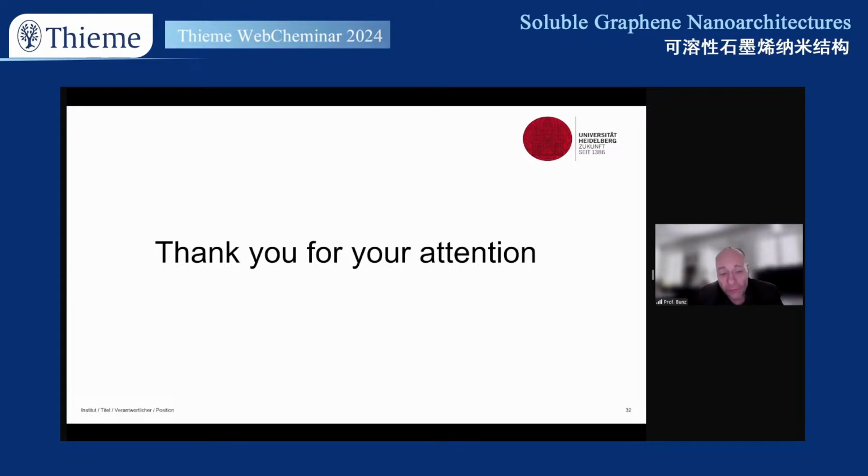One thing we have of course tried is, instead of the trichlorophenyl groups, we use what Professor Narita uses, the mesityl groups. But strangely enough, these heterocyclic diradicals seem to be more reactive than the pure hydrocarbons. And so we find four-membered ring formation by CH insertion and stuff like that. So it's a little bit different.